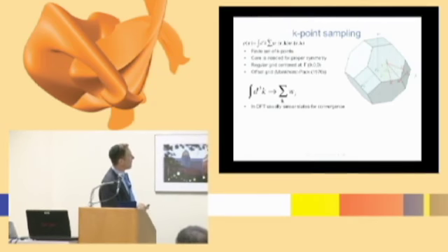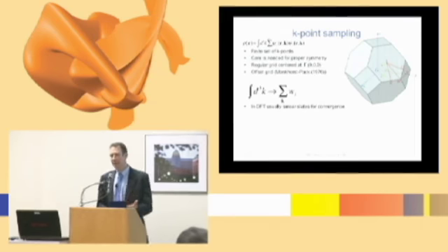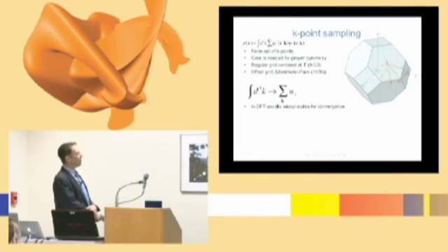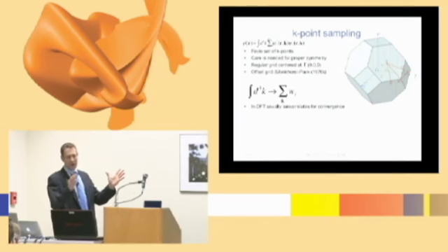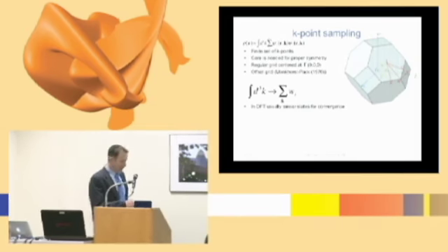There are different ways of sampling K-points to do this effective integral. Usually you use a finite set of K-points. You need to take some care so that you have the proper symmetry of the system when you do your K-point sampling. If your K-points don't have the symmetry of the system, you may predict improperly that the system should distort, and it really doesn't, and so forth.